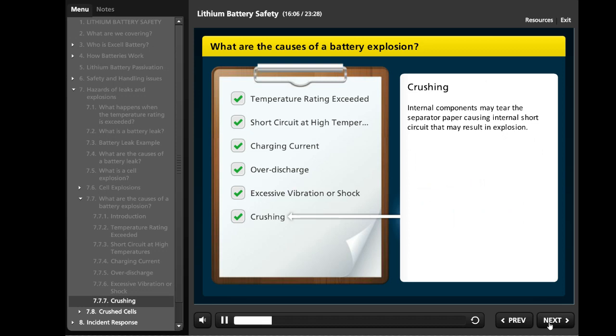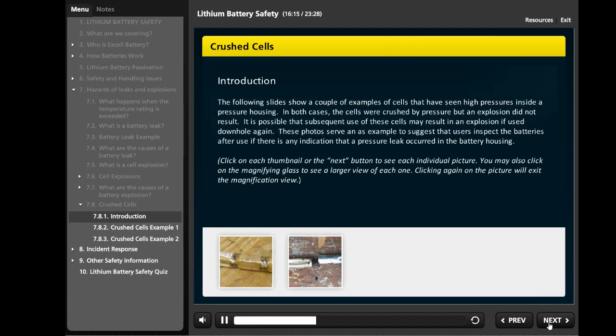If a cell is crushed, then internal components may tear the separator paper, causing an internal short circuit that may result in an explosion. These two pictures show a couple of examples of cells that have seen high pressure inside a pressure housing. In both cases, the cells were crushed by pressure, but an explosion did not result. It is possible that subsequent use of these cells may result in an explosion if used downhole again. These photos serve as an example to suggest that users inspect the batteries after use if there is any indication that a pressure leak occurred in the battery housing.